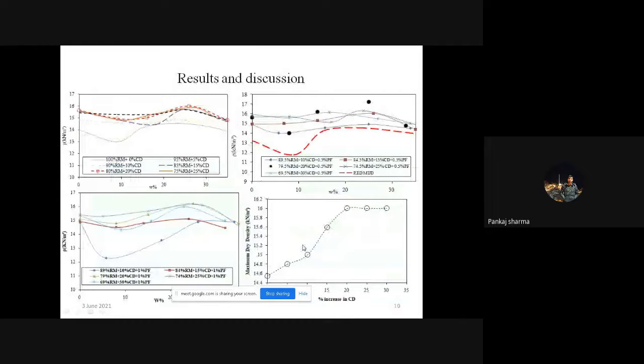From the results, first is the result discussion for the compaction test. From the curve, it seems like the dry density, with increase in the water content, starts decreasing, and then it starts increasing and attains its peak, which shows the bulking nature of the material. It seems like a sandy material which shows bulking. That means the density decreases up to some point, then attains its peak.